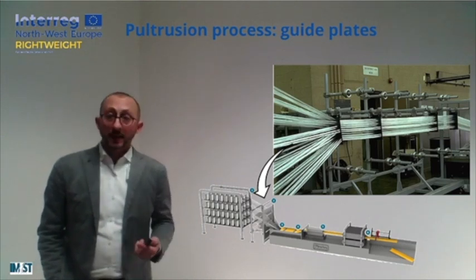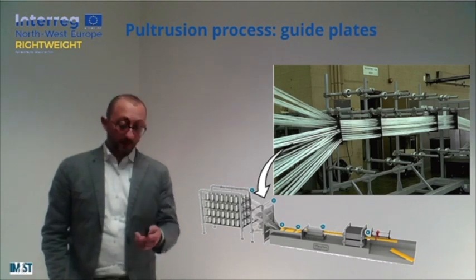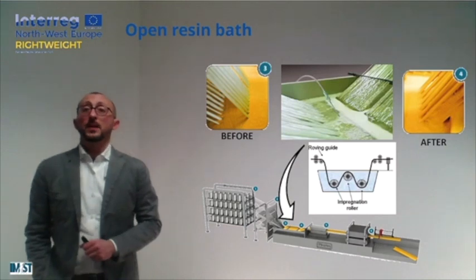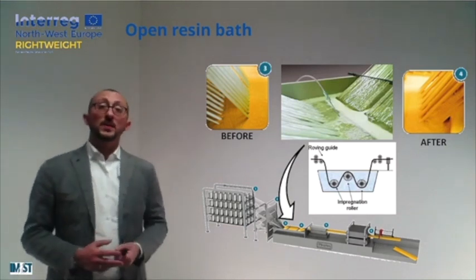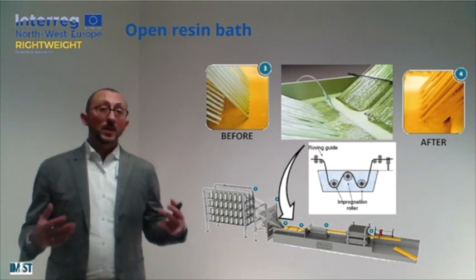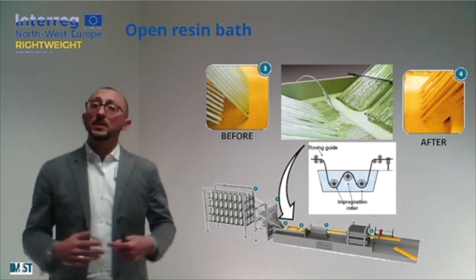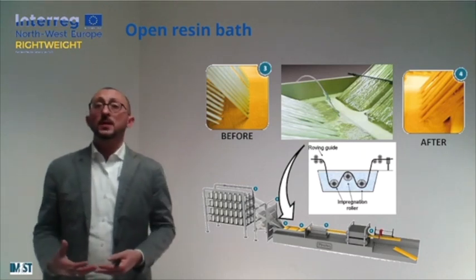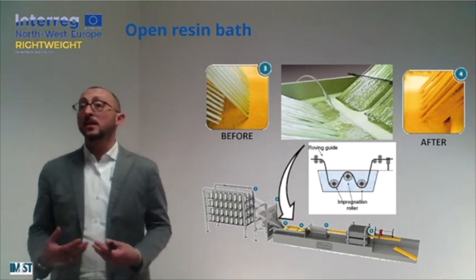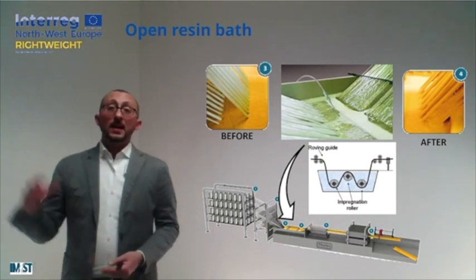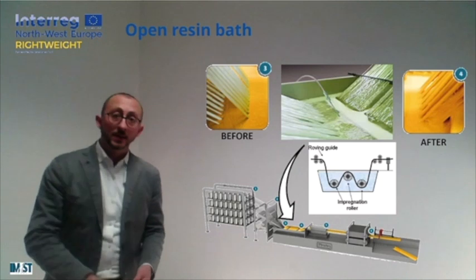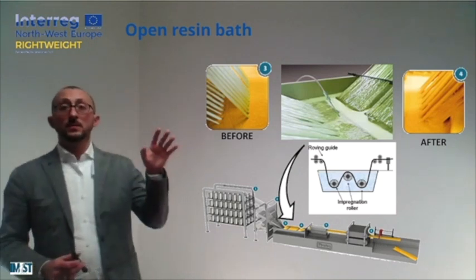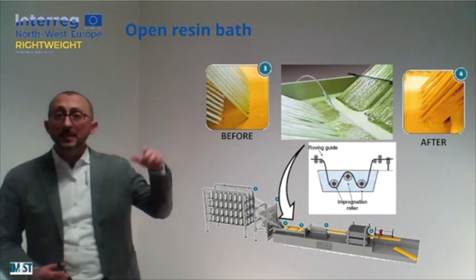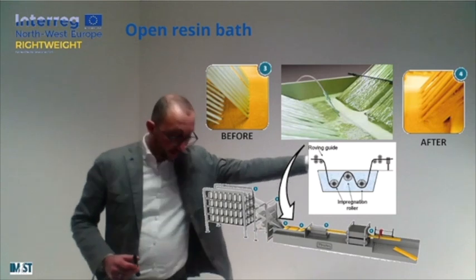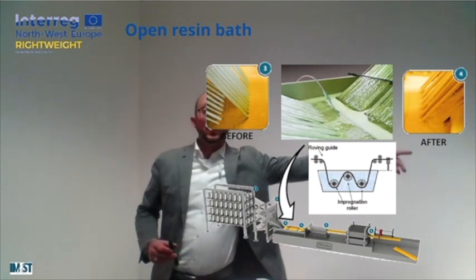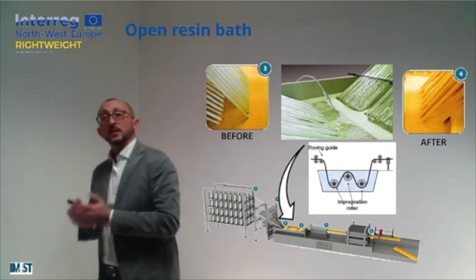At the end of the guidance plates, the impregnation step will take place. And in the conventional pultrusion line, this step is achieved using this open bath. Looking at the open bath, we can imagine this tank that is filled with catalyzed resin, ready to be used, ready for reaction, and the dry fibers are forced to dive inside this resin bath. So this is what we can imagine before going inside the resin bath, and after, at the end of the resin bath, the situation is more or less this one, with the fibers completely surrounded by our resin.